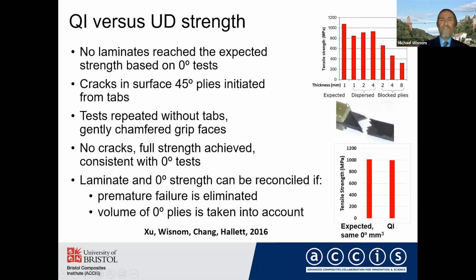So when Xiaodong noticed these cracks here, he decided to repeat the tests, this time without any tabs and using very gently chamfered grip faces in the test machine. And with this test method, he was able to eliminate these cracks initiating from the tab and managed to get the full strength. And so what we found was the strength of the quasi-isotropic did indeed match the strength you'd expect on the basis of the UD plies themselves, so long as the volume of the UD plies was taken into account. So what this shows is that the laminate and the 0-degree strength can be reconciled, provided you eliminate the failure prematurely, and also provided you take into account the volume of the 0-degree plies.